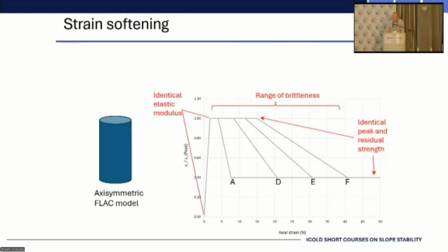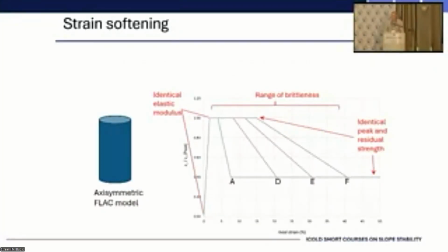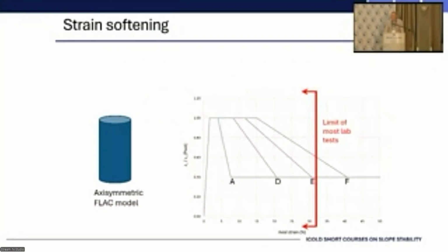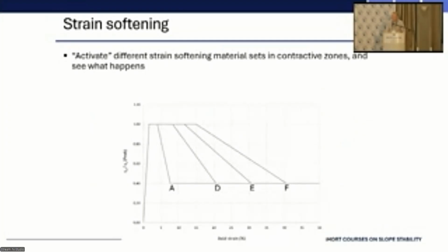Well, firstly, to point out that it's now effectively a range of brittleness, if we use the term brittleness to include the kind of strain over which the loss of strength occurs. But just emphasize, identical peak and post-peak. Identical initial elastic modulus. Also to point out that in a lot of laboratory tests, it's really hard to get beyond about 30% strain, probably 25% strain. And so we can sometimes lose that kind of behavior I'm indicating here. But what was done is to activate these different strain softening models in the contractive zone of that hypothetical problem I showed earlier and see what happens.